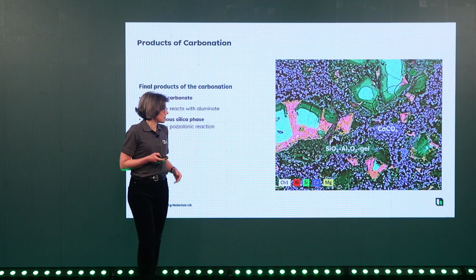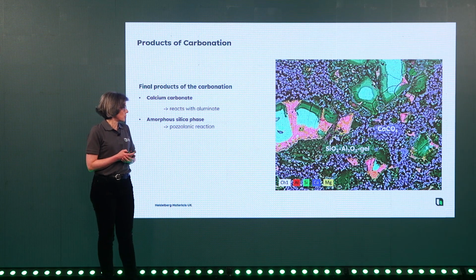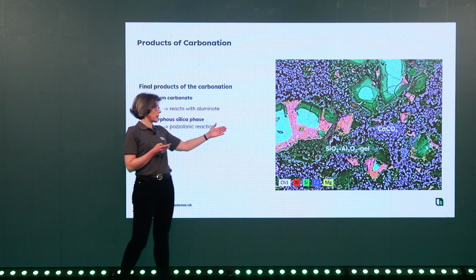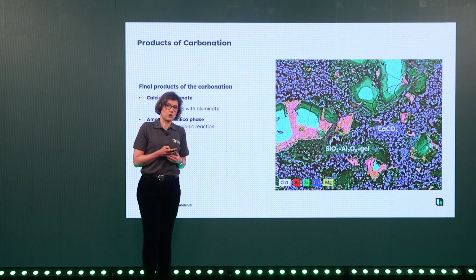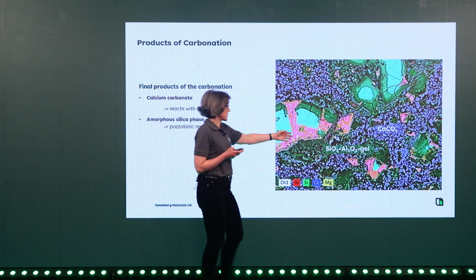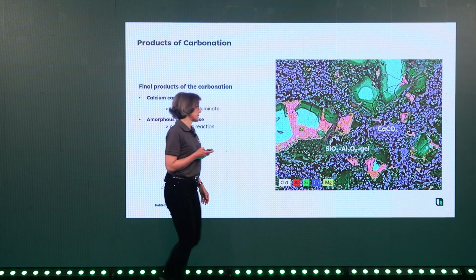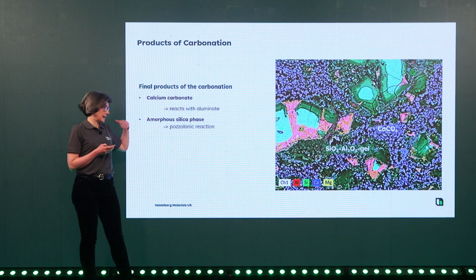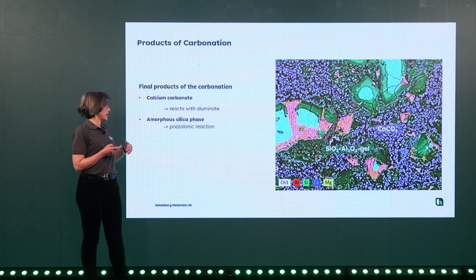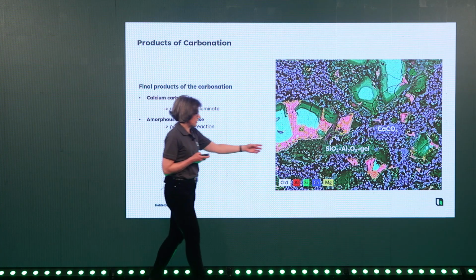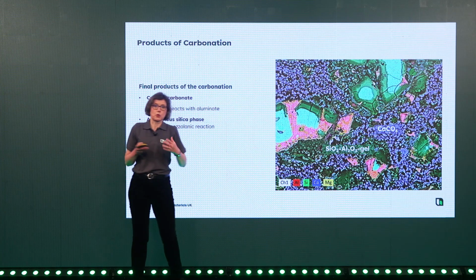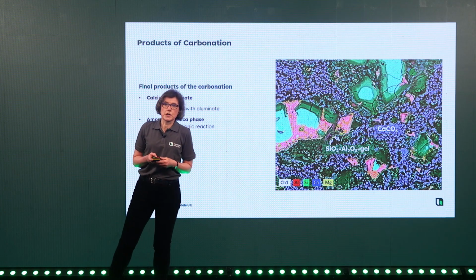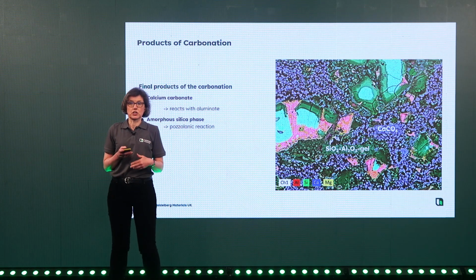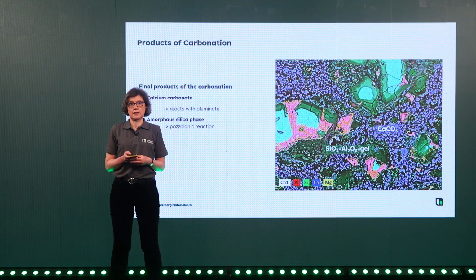No presentation without a good SEM photograph. What you see here is a photograph of carbonated recycled concrete paste. The purple areas are the calcium carbonates, and they react when they're added to cement and hydrate. They react with the aluminates. And we also see a silica alumina gel forming, which is a pozzolanic material, which we know already from GGBS or fly ash, which again gives strength to SCMs.